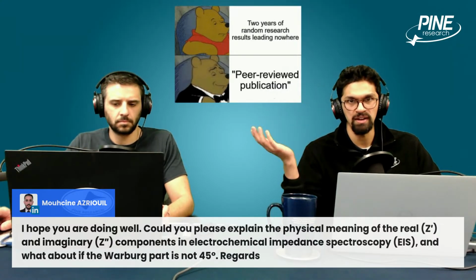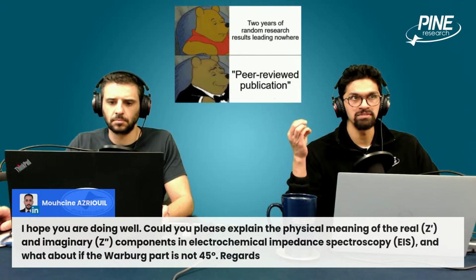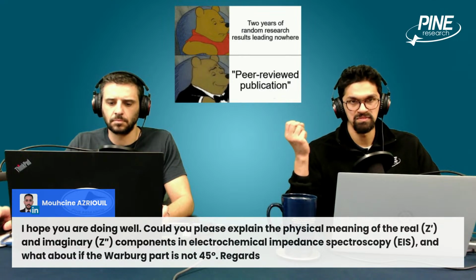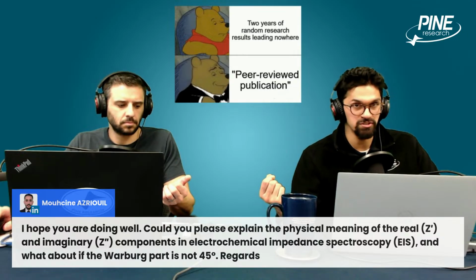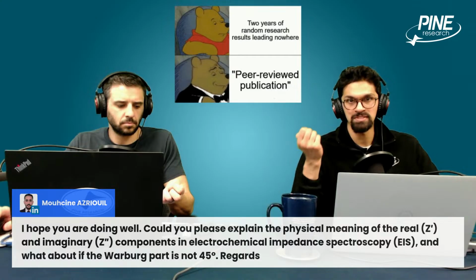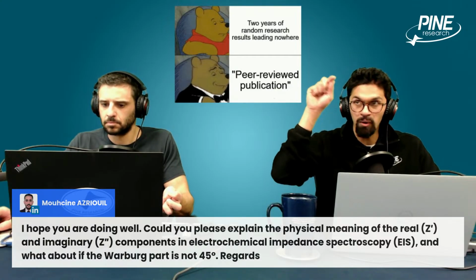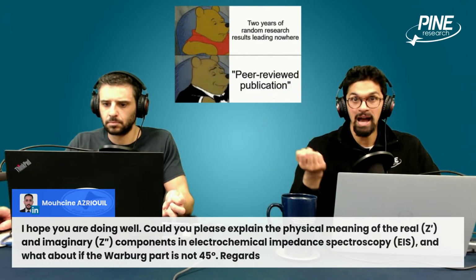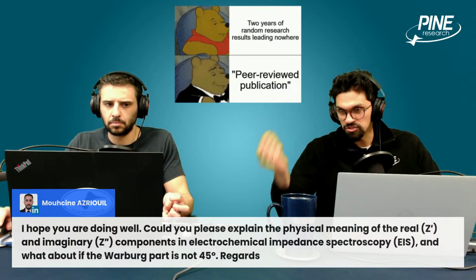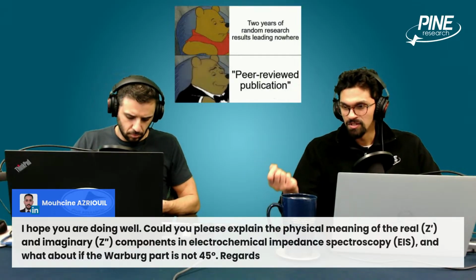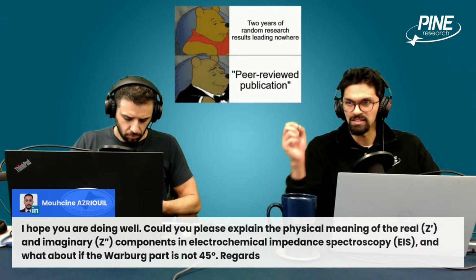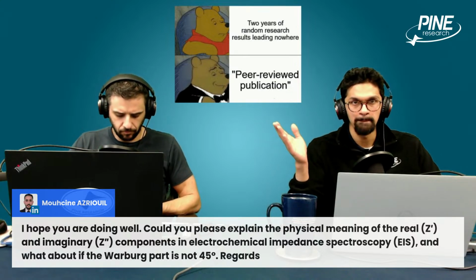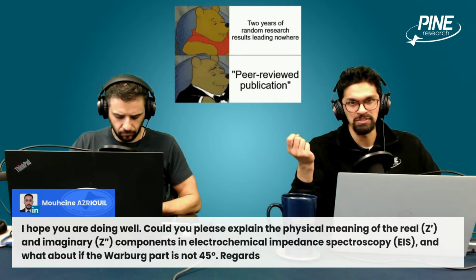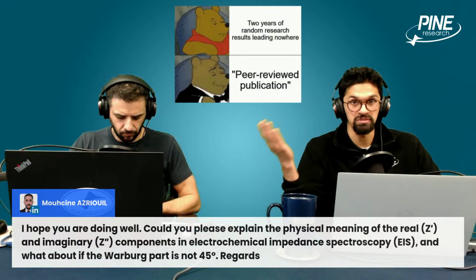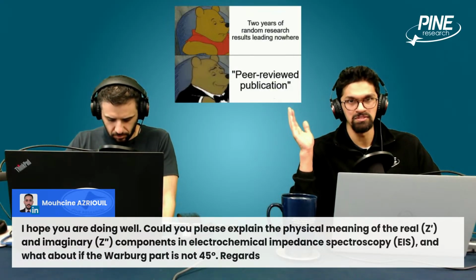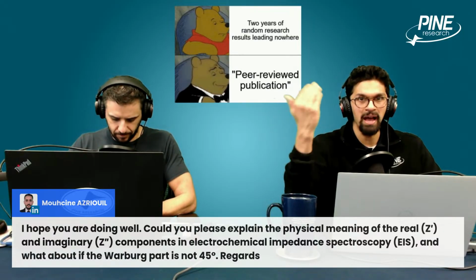So deviations from the 45-degree angle give you information about maybe my system is taking more time for charge to transfer, or less time for charge to transfer, given the frequency or the time scale of my EIS experiment. Every point on a Nyquist plot represents a time, right? It's a frequency. At very slow frequencies, when you give a system a lot of time, you only get real impedance. It means that the molecule had more than enough time to pass along charge, because it's current and voltage. So it was never delayed in time. It had the time to pass the charge back and forth.